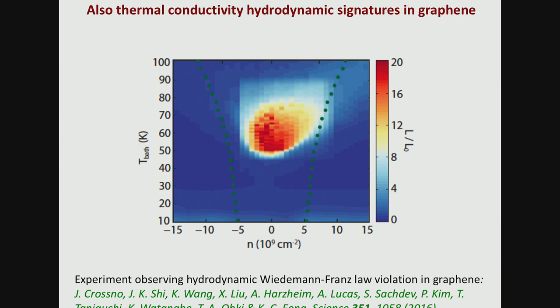So what they did, a very clever experiment in Philip Kim's group at Harvard, and they found a very clever piece of graphics, which always helps you sell your results, where they show that blue here is the Wiedemann-Franz law being obeyed, and red, yellow and light blue are violations, with this nice deep red being the biggest violation. So they're seeing about a factor of 20 violation of the Wiedemann-Franz law in this region of their phase diagram, very near, clustered around the charge neutrality point, and at about 60 Kelvin.